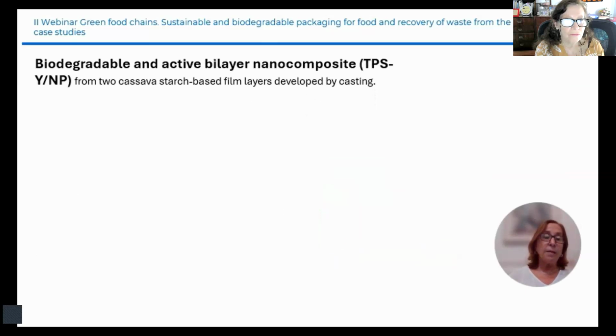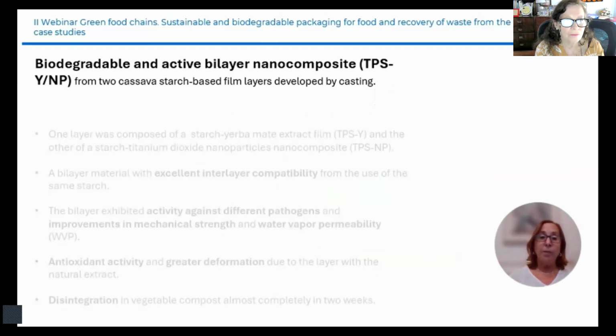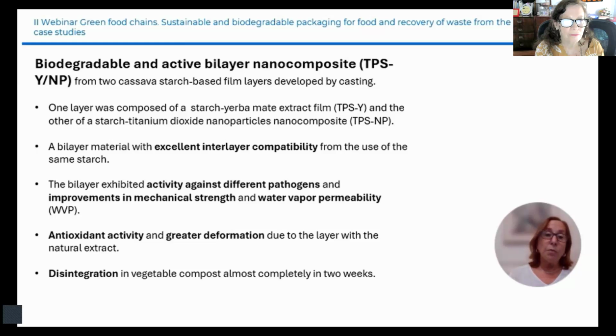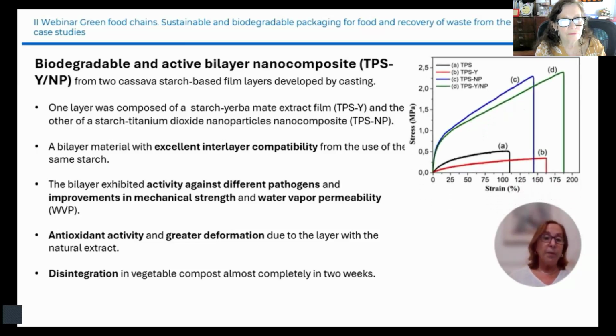After the previous results, we also developed biodegradable and active bilayer nanocomposites from 2 cassava starch-based films. One layer was composed of a starch yerba mate extract film, and the other was a starch titanium dioxide nanocomposite. The bilayer material presented excellent interlayer compatibility from the use of the same starch in both matrices. The bilayer also displayed activity against different pathogens and improvements in mechanical strengths and water vapor permeability.